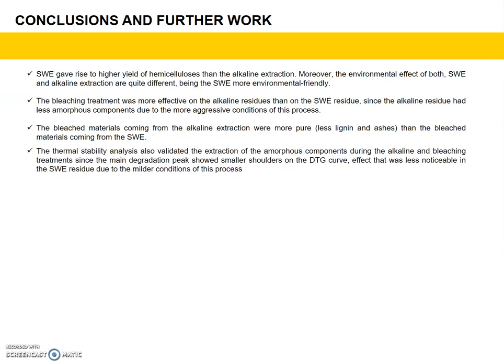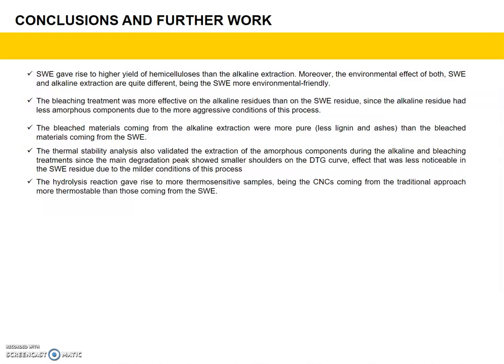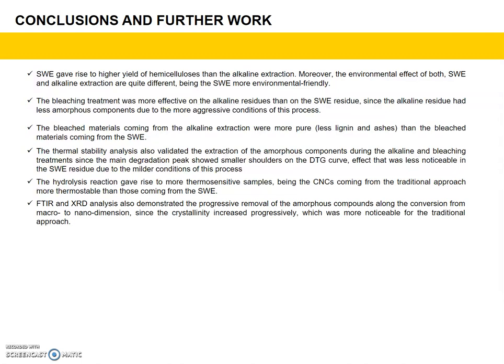The thermal stability analysis also validated the extraction of the amorphous component during the alkaline and bleaching treatments, since the main degradation peak showed a smaller shoulder effect that was less noticeable in the subcritical water extraction residue due to the milder condition of this process. The hydrolysis reaction gave rise to more thermosensitive samples, the CNC coming from the traditional approach being more thermostable than those coming from the subcritical water extraction. FTIR and XRD analysis also demonstrated the progressive removal of the amorphous component along the conversion from macro to nano dimension, since the crystallinity increased progressively, which was more noticeable for the traditional approach.